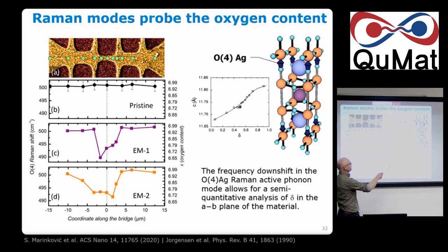So with Raman, we investigate the mode in which these oxygens are moving, like the blue arrows here. These oxygens, we don't touch them with electromigration, but they are very sensitive. The length is very sensitive to what you have on the chains. So what happens is, delta is in the equation of YBCO, O7 minus delta. So delta equal to 0 means you are a perfect conductor, superconductor. As delta increases, you make it more and more insulating towards the antiferromagnetic phase.